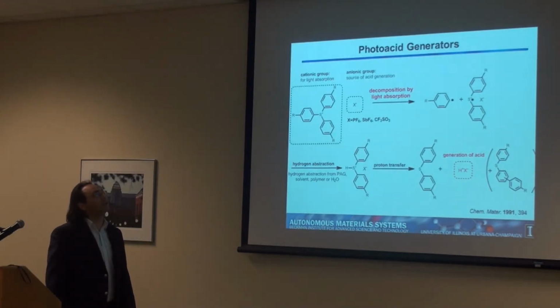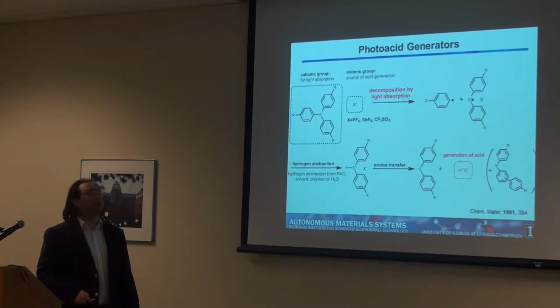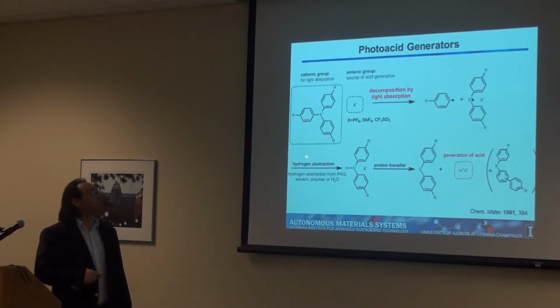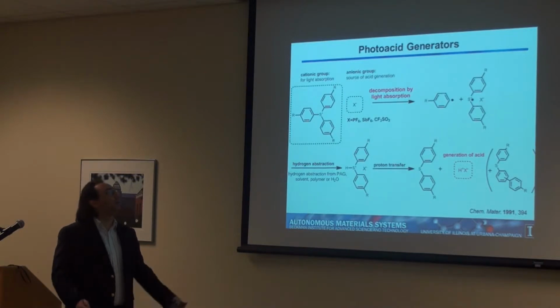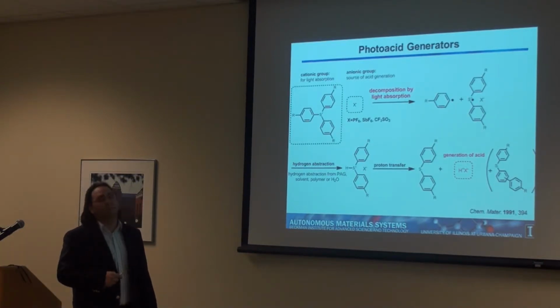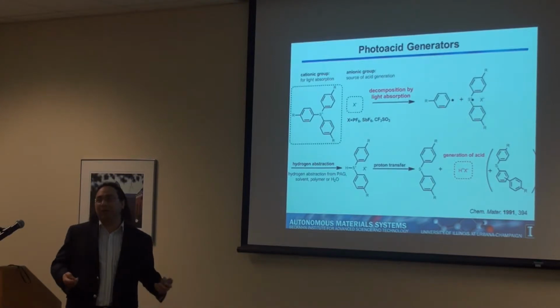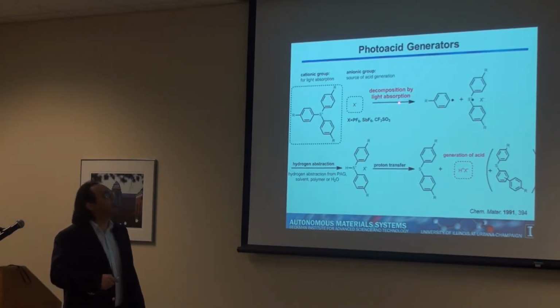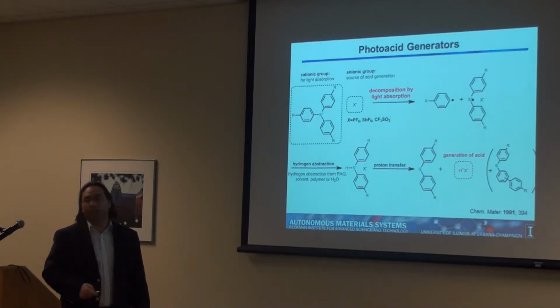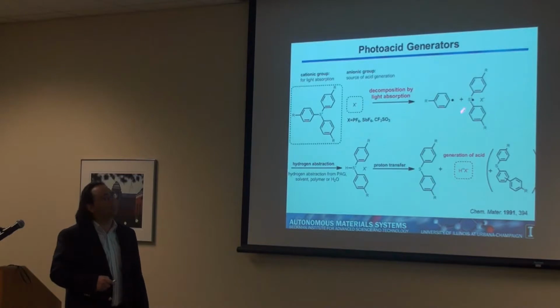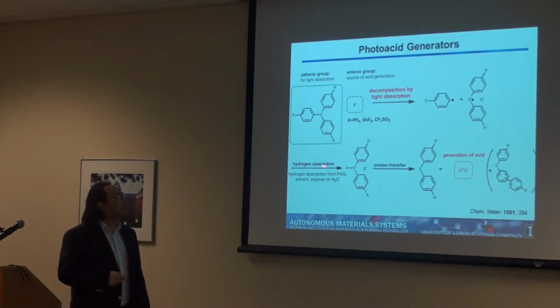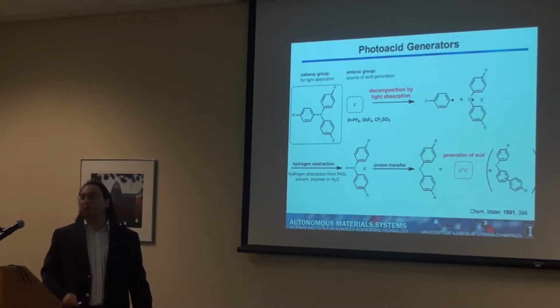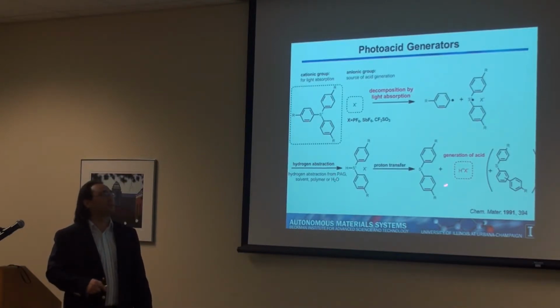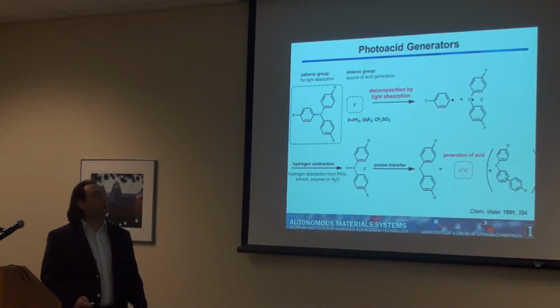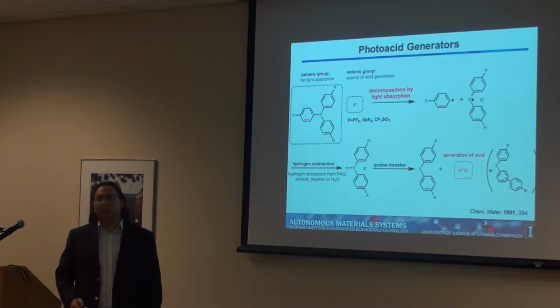And for that, we decided to look at photoacid generators, which are very thermally stable. The most common, most used form of photoacid generators is the sulfonium salt. The mechanism by which it works is that when you shine UV light, you break this carbon-sulfur bond, producing two radicals. The sulfonium radical is extremely reactive. It basically abstracts a hydrogen from anywhere around that it can, and basically it produces the acid that we want. And we were thinking, well, can we do this same reaction by mechanical force?